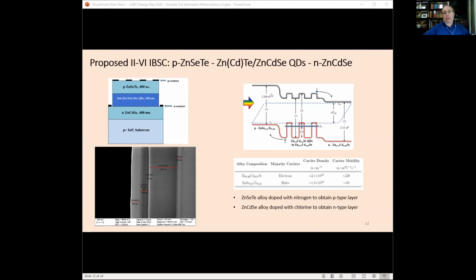So this is for the experts in physics, the schematic of the band diagram. You don't have to worry about that, except to look at this open circuit voltage calculation, which is close to 1 electron volt and would be important to see how our progress is. We actually can grow a p-type layer and n-type layer successfully, which is shown in this table. And this is an SEM image of a grown prefabricated device. You don't have a device, it's just the material which the device has to be made of.